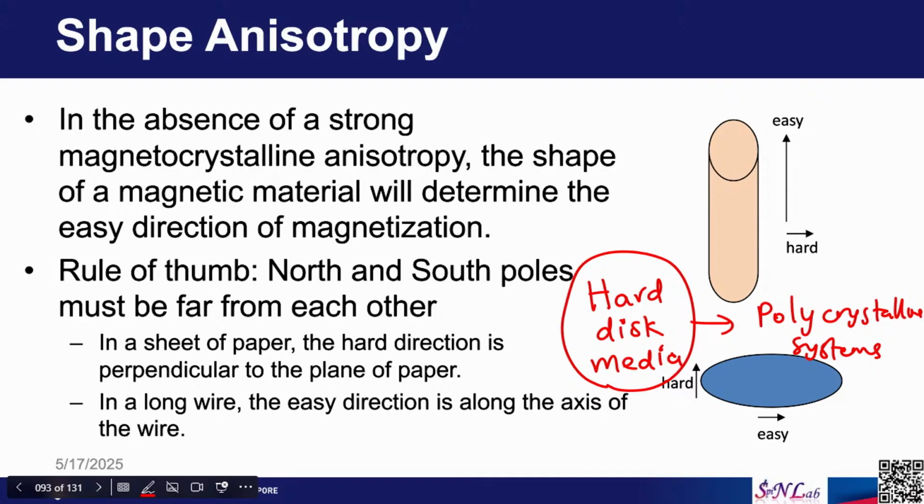In this system we have tiny crystals separated from each other, and in the recent hard disk drives these grains have magnetic anisotropy in the perpendicular direction. So, their magnetization may either point into the board or point away from the board, and these are usually highly textured films.